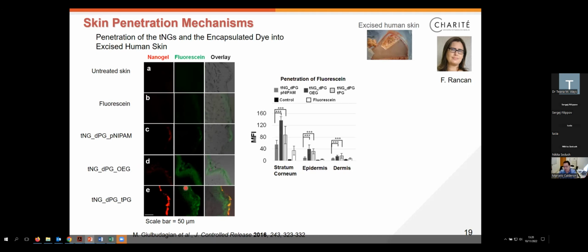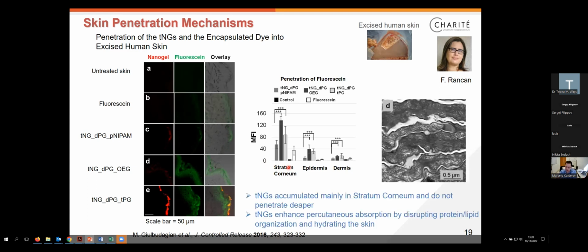We quantified this. We could correlate this with some of the properties of the nanogels. Sorry that we're not going into the details on that because of the time. But what I can tell you is that we could see very nicely that by fine-tuning some properties of the nanogels, we could enhance the penetration of the cargo molecule inside of the skin. But in all cases, the nanogel gets stuck in the stratum corneum, which is interesting to see, of course, and it's somehow an obvious result.